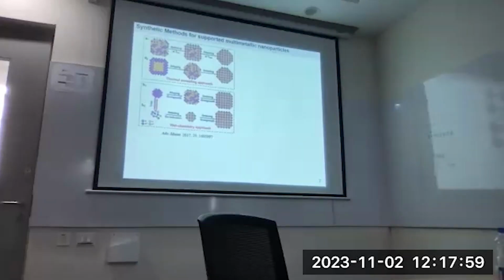So yeah, there are many. I'm not going to go too deeply into this. These are papers that we've published. Basically, these are all using solvothermal methods. We use liquid solvents, we put the metal salts inside, and we heat it to a maximum of around 400 degrees Celsius. We can form nanoparticles based on how these metal atoms interact with each other.